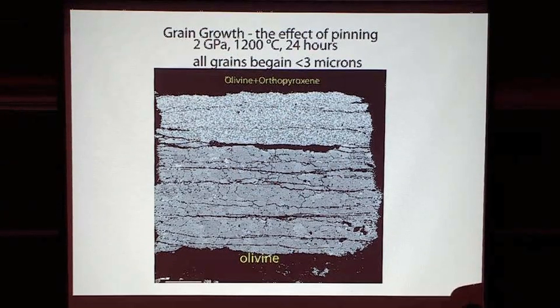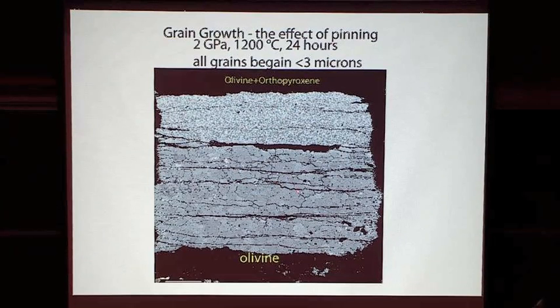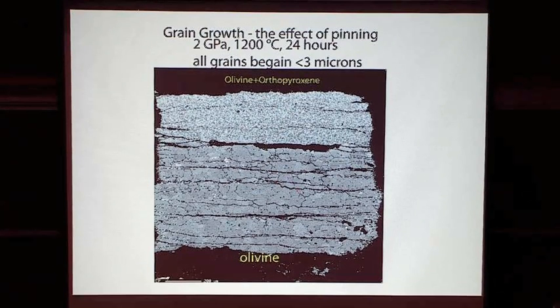But Mark, this diffusion depends on vacancies. So wouldn't you expect vacancy numbers to depend on pressure then? No, this kind of grain growth doesn't depend on vacancies in the crystal. The grain boundaries themselves are the fast paths, right? It's the things that are being eliminated by the grain growth. So no, it doesn't require intracrystalline vacancies.